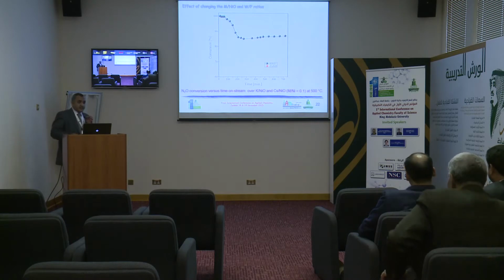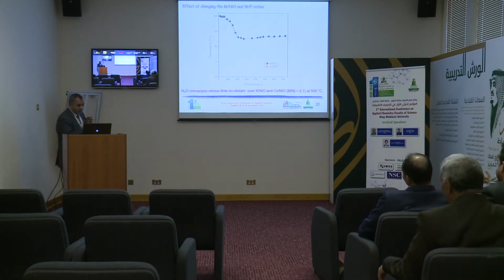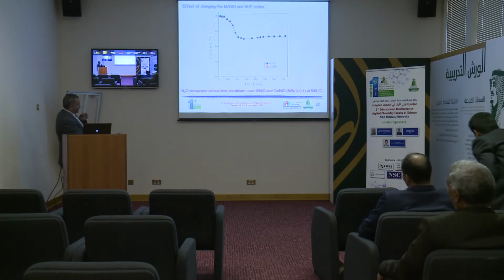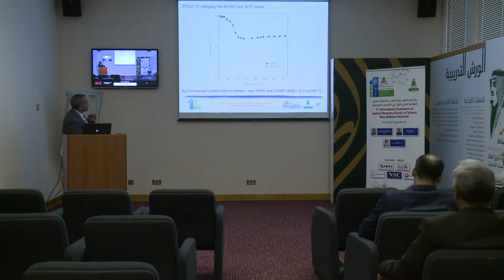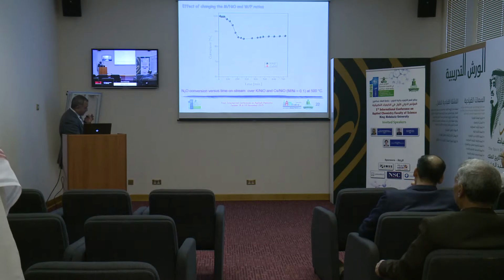I have one more slide. Going to the effect of time on stream for the two most active catalysts, we can observe that the activity of the potassium catalyst slightly decreased with time, then it stays constant until around 10 hours.